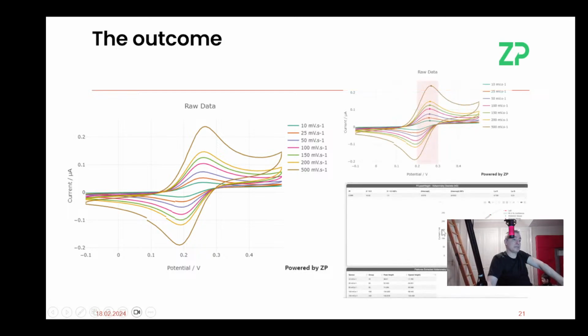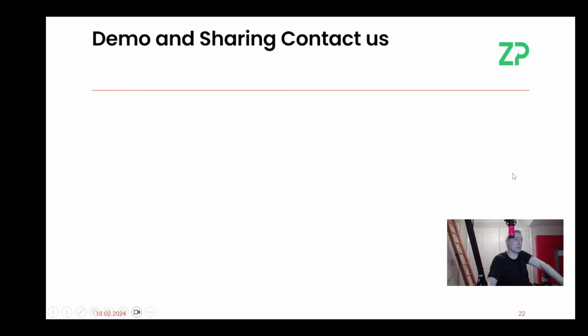So we can take data like this and use Julia to do what we call peak finding, and then we can plot current versus the square root of scan rate, and we get a really good fit, because the Randles-Sevcik equation is quite a robust way of analysis. I want to say it always works. It works if you've got a fairly well-behaving electrode, and your redox molecule is in solution, under diffusion control, and fairly reversible. Then the Randles-Sevcik equation works a lot.